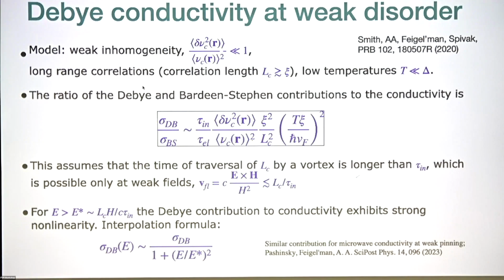We assumed weak disorder, so that the variance of the density of states fluctuations is relatively small, and the disorder has long-range correlations where the correlation length exceeds the core size. Then you can obtain this ratio of the Debye conductivity to the Bardeen-Stephen conductivity in the following form. There's this big ratio of inelastic to elastic relaxation time, and then a bunch of small parameters which describe the strength of disorder and correlation rates.